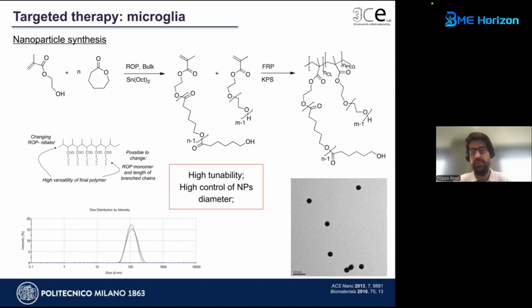But before saying what we found, the strategy we use to treat selective microglia is to obtain, in this case, not a nanogel that we use in the second part of this talk, but a classic polymeric micelle that self-assembles due to the presence of an amphiphilic polymer, so a hydrophobic part and a hydrophilic part, and then with nanoprecipitation we can create the nanoparticle. We started with the preparation of the macromonomer, from left to right, using hydroxyethyl methacrylate and caprolactone, with ring opening polymerization to open the ring of caprolactone. In bulk conditions, we obtained the macromonomer. We added to this macromonomer hydroxyethyl methacrylate linked with PEG. In this case, PEG is fundamental for the stability of the system, to avoid aggregation and instability of the colloidal form at the end.